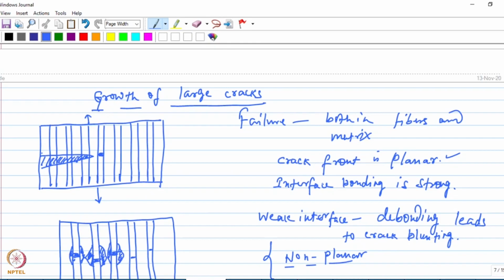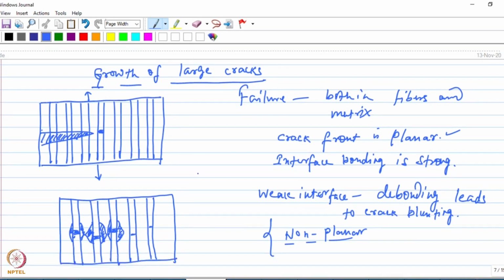Okay, and then we talked about growth of a large crack under a tensile load in the fiber direction. So here again, depending on the interface bonding, the fracture can be planar or non-planar. When the bonding is strong, it will be planar. The matrix crack will follow the fiber crack, and these two cracks will be in the same plane. On the other hand, if it is a weak interface, debonding leads to crack blunting effects, and here the fracture of the fiber and the matrix are not necessarily in the same plane, so this will be a non-planar type of fracture. And with that, we come to the end of this lecture.